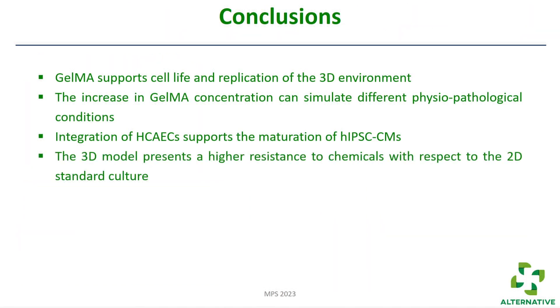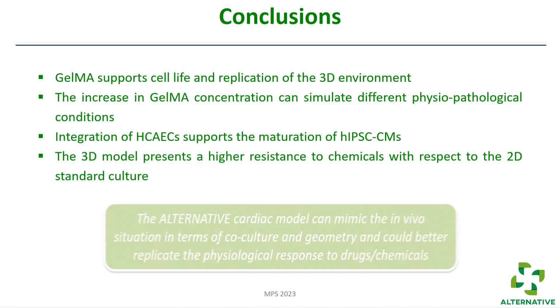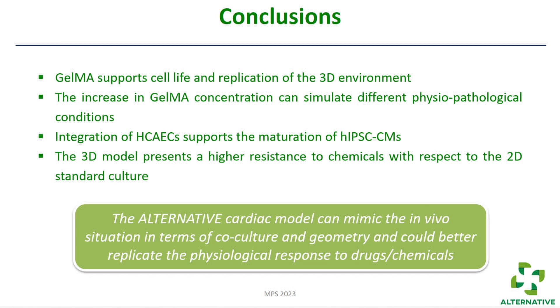To conclude: GelMA supports cell viability and replicates the environment. Increasing GelMA concentration can simulate different physiopathological conditions — in particular, we want to simulate aged cardiac tissue. Integration of endothelial cells supports maturation of cardiomyocytes. The 3D model presents high resistance to chemicals compared to standard culture, which is important for translation to the in vivo situation. Our alternative cardiac model can mimic the in vivo situation in terms of co-culture and geometry. In the next phase, we will integrate a 3D-printed scaffold and culture our system in a sensorized bioreactor.